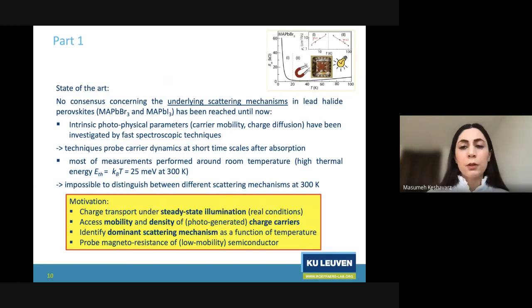So the motivation for this part was, first of all, to do charge transport under steady-state illumination, which is the real working condition of perovskites in the cells or photovoltaics, and then access the mobility and density of charge carriers, identify dominant scattering mechanism as a function of temperature, and also probe magnetoresistance in these low mobility semiconductors.